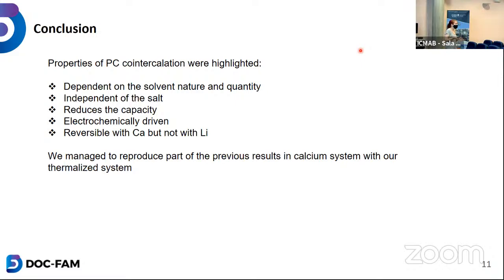We have a difference between lithium and calcium. In the lithium system, you have no way of removing the co-intercalated propylene carbonate, but with calcium, it seems to be quite reversible. And as a conclusion, we managed to reproduce part of the previous results because in one cell, we managed to do the calcium intercalation, but not to retrieve the starting material. And with another cell, we managed to have full reversibility of the co-intercalated phase, but not to have the calcium intercalated phase. So maybe one day we will be able to do both in situ.